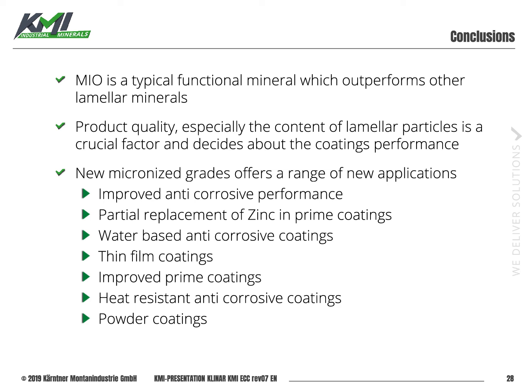Micaceous iron oxide is a typical functional mineral which really outperforms other lamellar minerals like micas, for example. The product quality, especially the content of laminar particles, is a crucial factor and decides about the coating's performance. And with the new micronized grades, there is no longer a limitation of the minimum dry film thickness. The necessary loading levels are lower, and this offers a range of new applications like coatings with improved anti-corrosive performance, partial replacement of zinc in prime coatings, water-based anti-corrosive coatings, thin film coatings, improved prime coatings, heat-resistant anti-corrosive coatings, and also powder coatings.